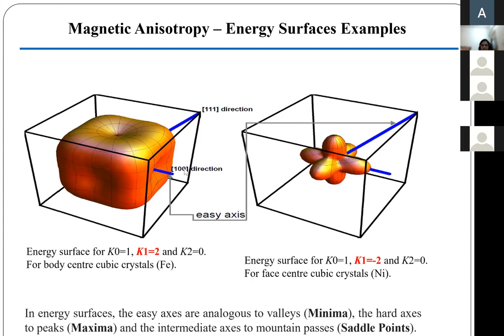So 100, 010, 001. On all these directions, there is a local minimum in the energy. And then there are peaks along 111. So the easy axis clearly is the one that minimizes the magnetocrystalline energy, and the hard axes are the ones where the magnetocrystalline energy is the maximum.